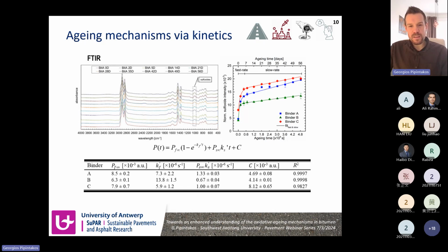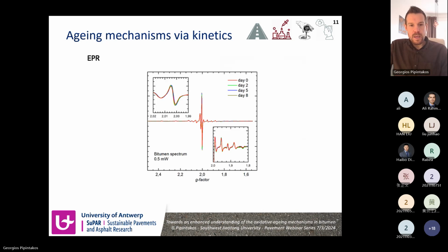So the idea was that 50 degrees was used in order to have a temperature closer to real in situ conditions. Also, as mentioned in the hypothesis for the aging mechanism, we could have also formation of radicals. EPR is a technique that can identify both radicals, but also unpaired ions.